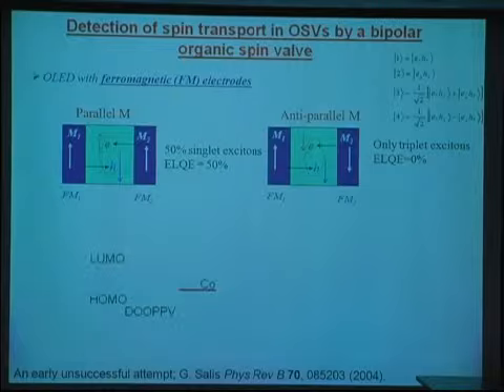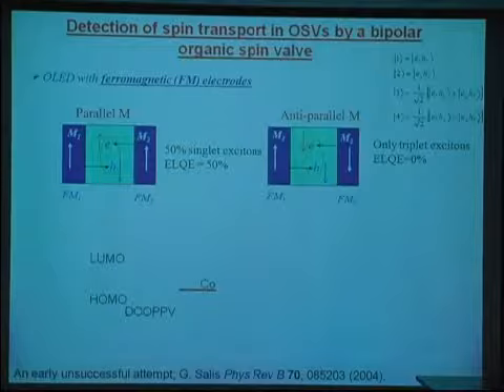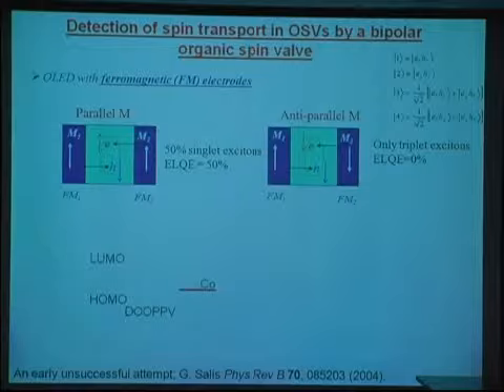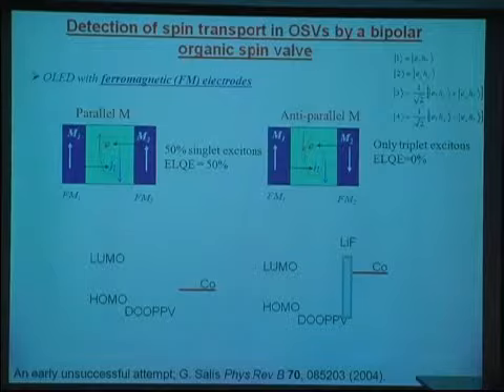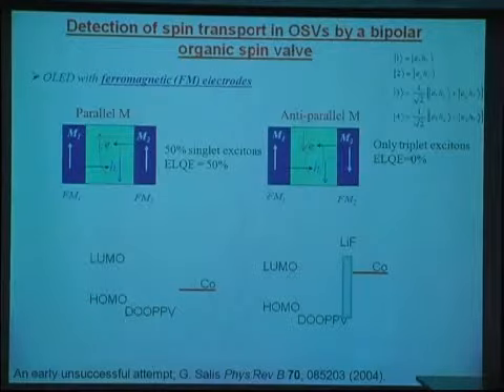Okay, but the question is how to inject spin-aligned electrons into the materials. So we use cobalt. Cobalt has the Fermi energy next to the HOMO level of DOOPPV. This is not good for electron injection. But in the organic light-emitting diode community, people have studied this phenomenon a lot. If they put lithium fluoride, an insulating material, next to the cobalt, they change the work function of the cobalt. They can shift the energy level of the cobalt up close to the LUMO level. So at that point, cobalt can be used to inject electrons into the organic semiconductor.